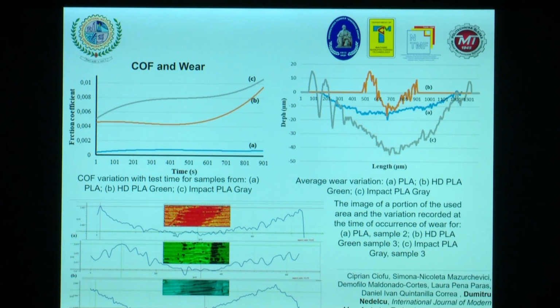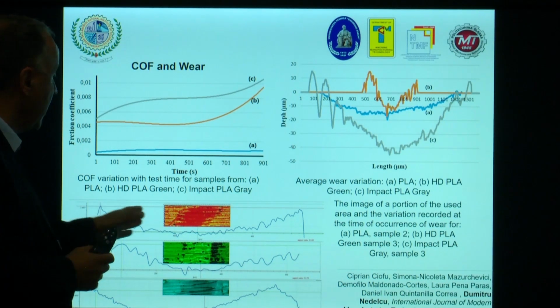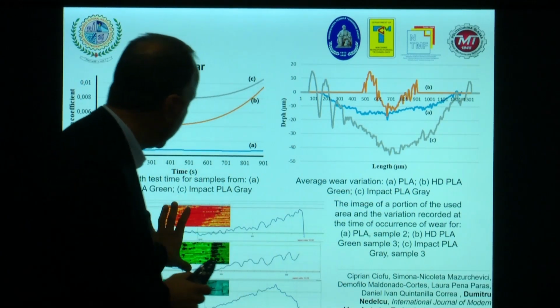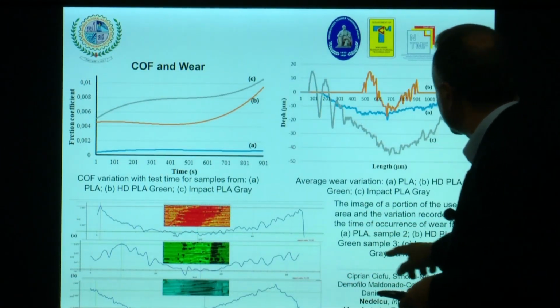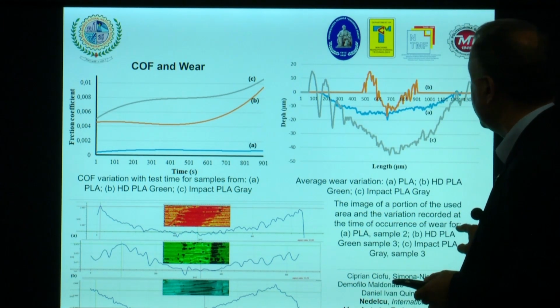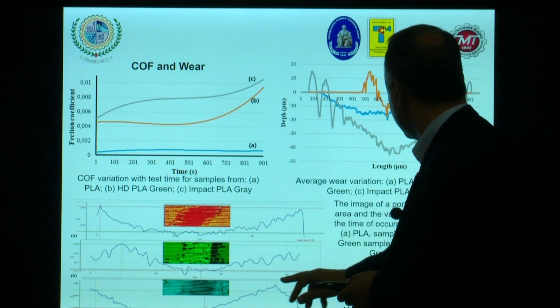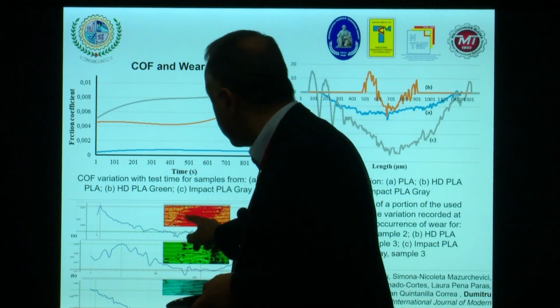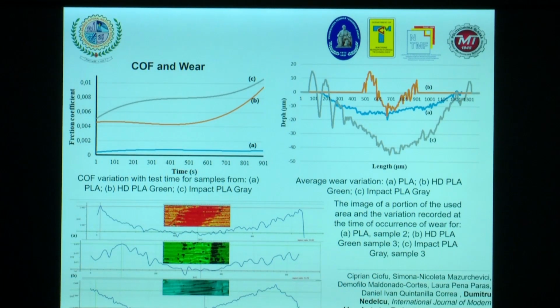PLA. We study also the wear, what happened to the wear during the loading force. So you can see on the left side the image of the portion of the used area and the variation recorded in time of the occurrence of the wear for PLA sample, high density PLA, and impact PLA gray. Of course, you can see over there some damaged areas because of the melting temperature, and of course maybe other factors.